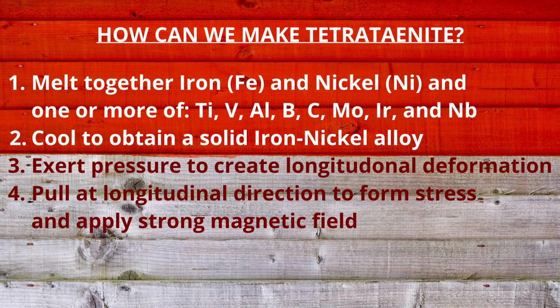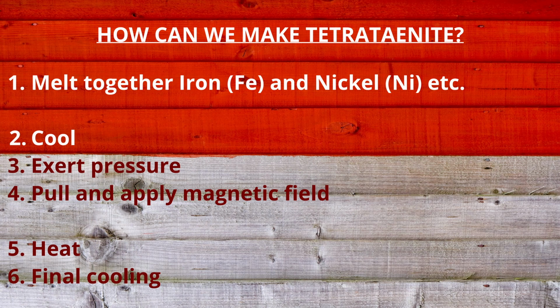The solid is then pulled in the longitudinal direction to form extensional stress, and a magnetic field is then applied along that direction. Then, in a reduced oxygen environment, the solid is heated again to a temperature which is higher than the chemical ordering temperature of L10 tetrataenite. Finally, the solid is cooled to a temperature which is lower than the chemical ordering temperature of tetrataenite, and at this stage the magnetic FeNi alloy material containing L10 ordered structure is obtained. Overall, the process is pretty simple. Just heat, cool, press, pull, magnetize, heat and cool again, and you have tetrataenite. But the devil is in the details, and the process still requires optimizing.